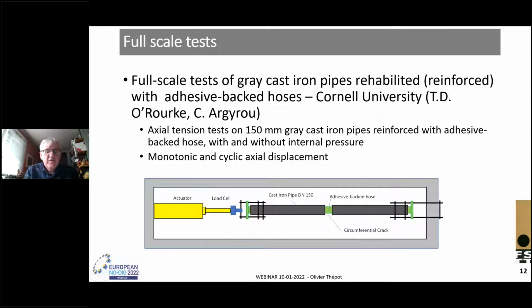I now present full-scale monotonic and cyclic uniaxial tensile tests that were recently performed at Cornell University, USA, on gray cast iron pipe with circumferential cracks or weak joints, reinforced with bonded interior lining. The objective was to assess the ability of the lining to accommodate large axial deformation. The test device comprised 2 gray cast iron 150 mm pipe sections, separated by an opening of 6 to 12 mm or by a joint.